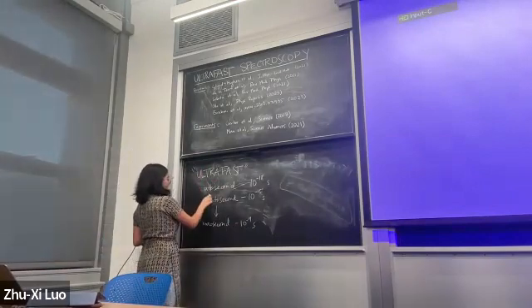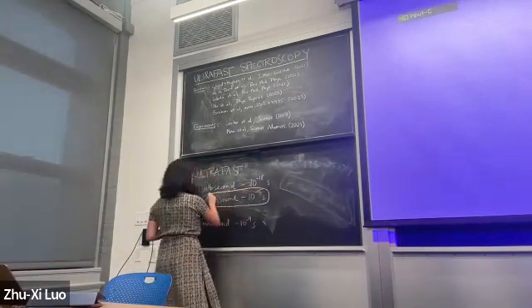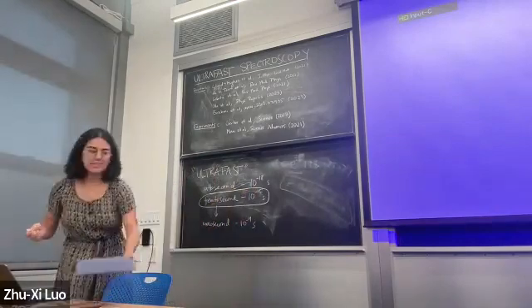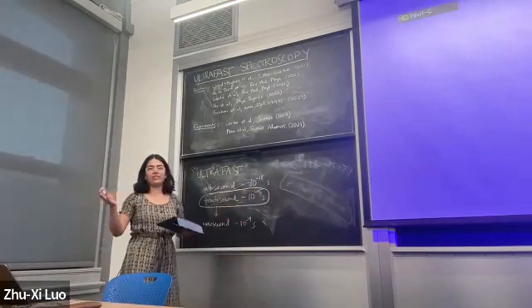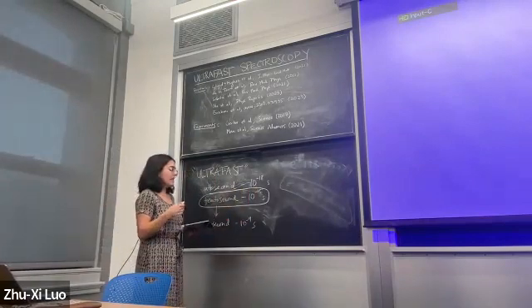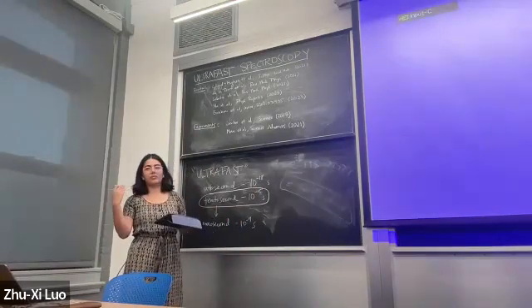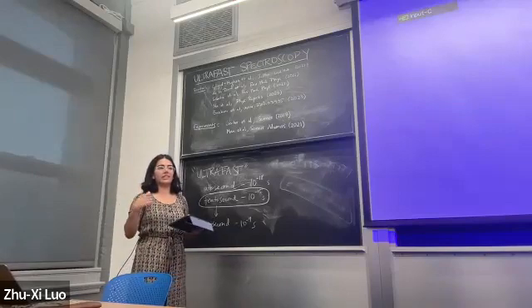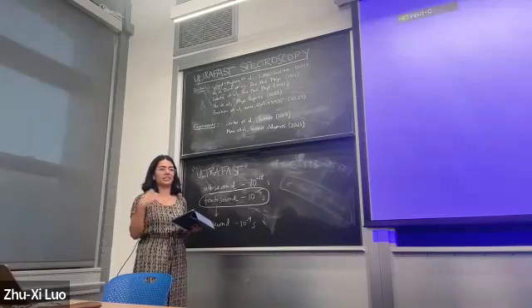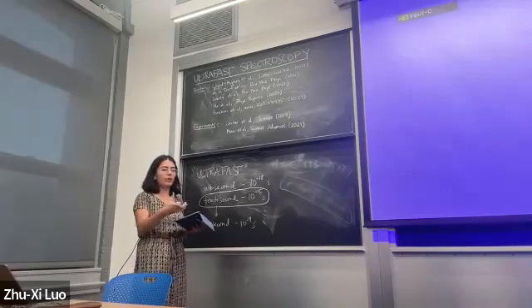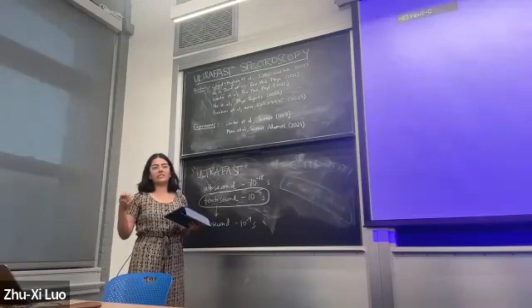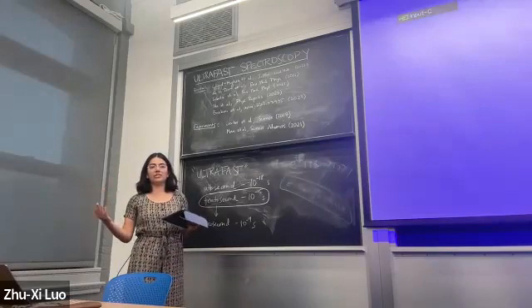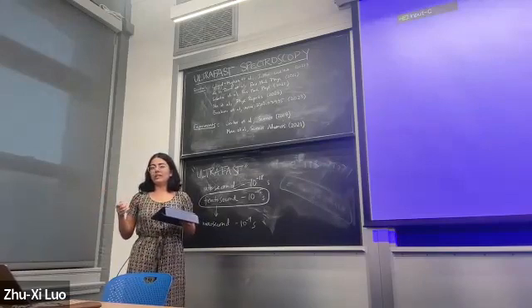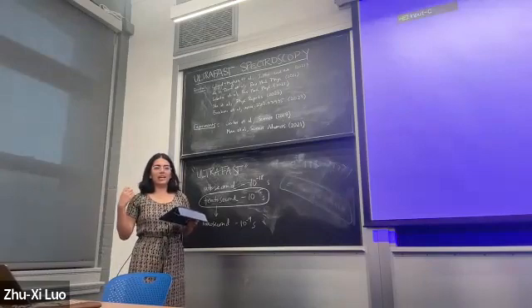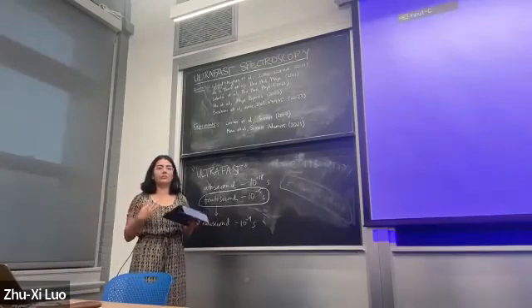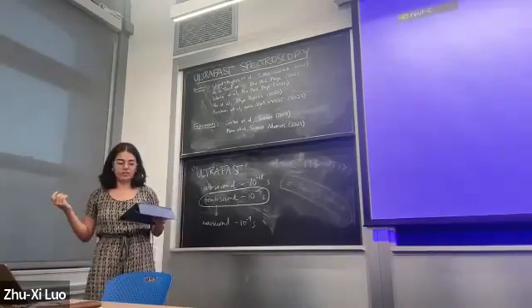But why do we care about femtosecond in particular? This is because femtosecond and picosecond, around 10 to the minus 15 to 10 to the minus 12 seconds, are the timescales on which the fundamental interactions in materials are happening, like electron-electron interactions and electron-phonon interactions. And so if we can probe the dynamics of our materials with this sort of time resolution, we can get insight into the actual underlying mechanisms that give rise to the emergent phenomena that we see in a wide range of condensed matter systems.